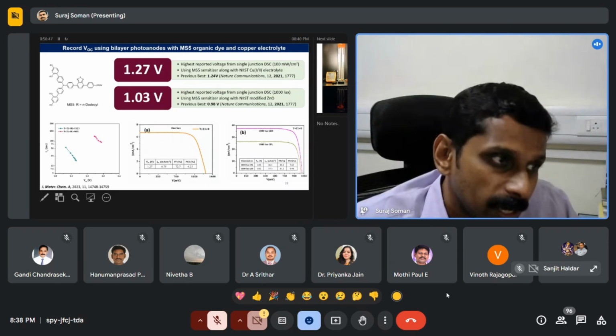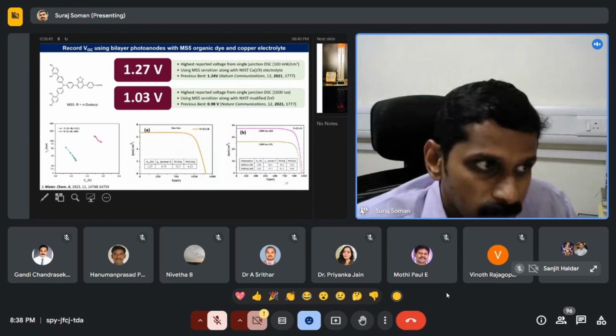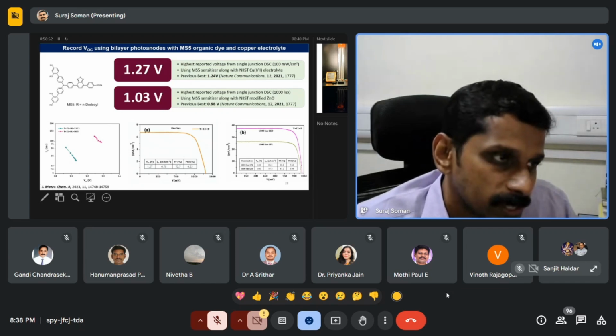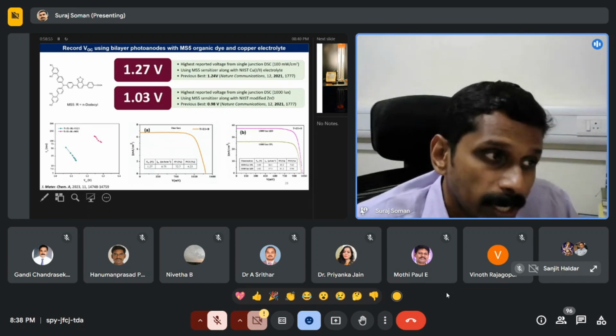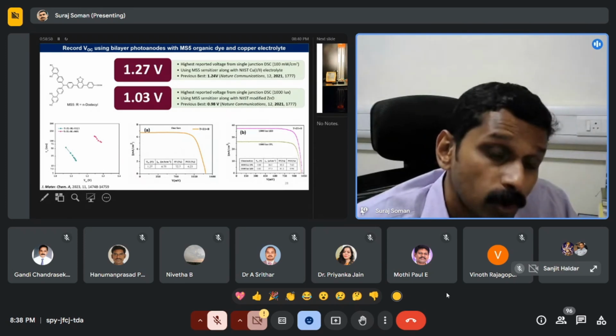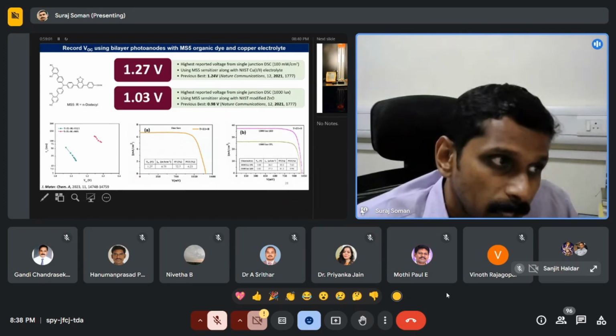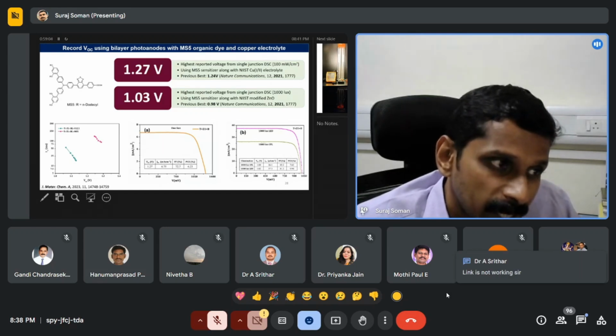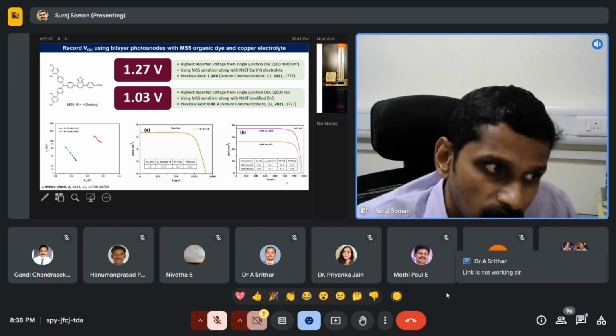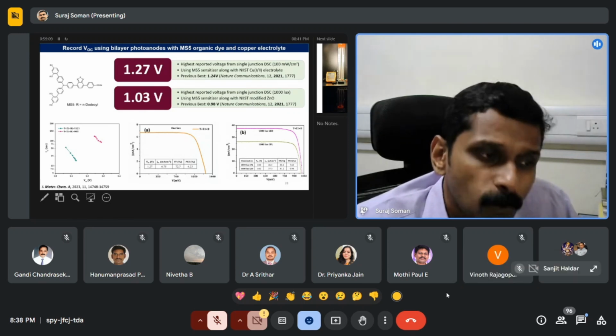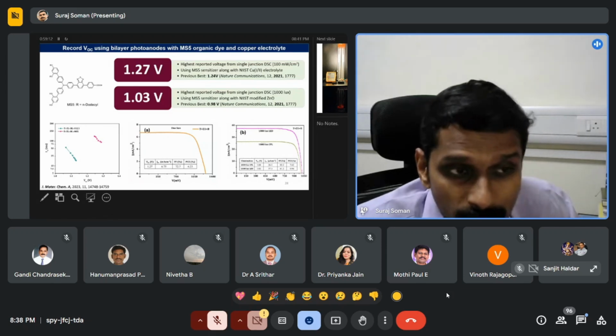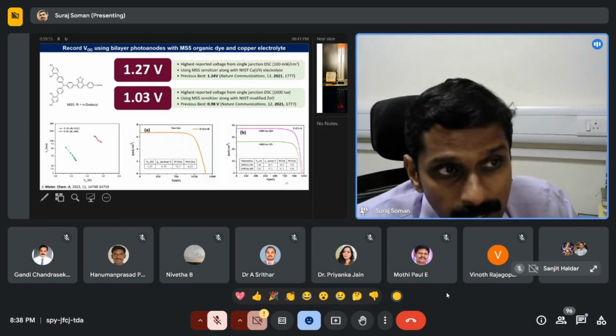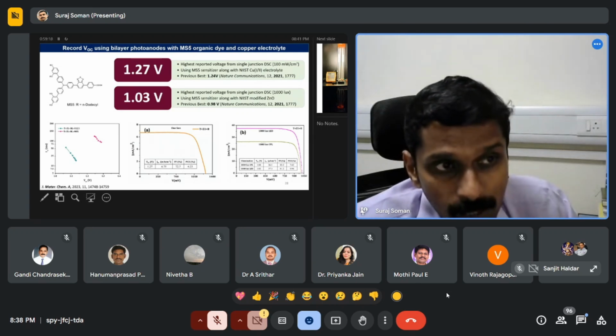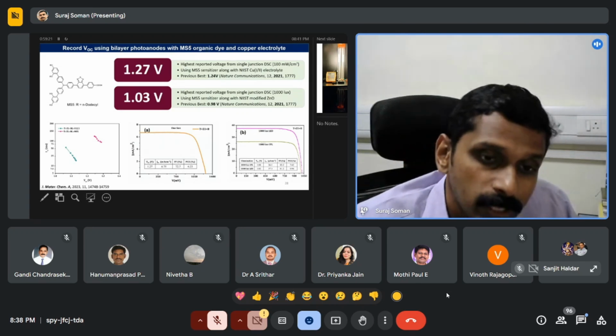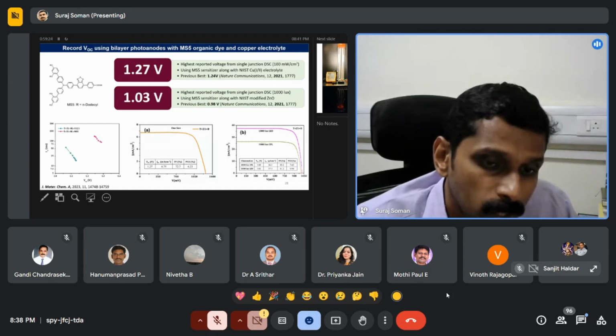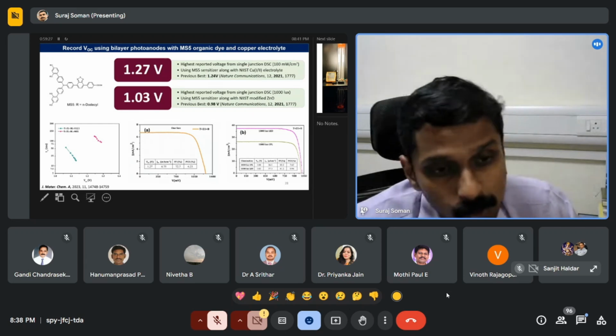So there we introduced this MS5 sensitizer. This sensitizer is also a triphenylamine based sensitizer, but it has dodecyl groups attached to the periphery, which is more effective in preventing the recombination. By using that dodecyl group, you can see that this one is for the Y123, the star one is for the MS5. There is a couple of orders improvement in the lifetime, and that actually helped us realize a record voltage of 1.27 volt from a single junction device. This was presently also the highest reported voltage from a single dye sensitized solar cell device.